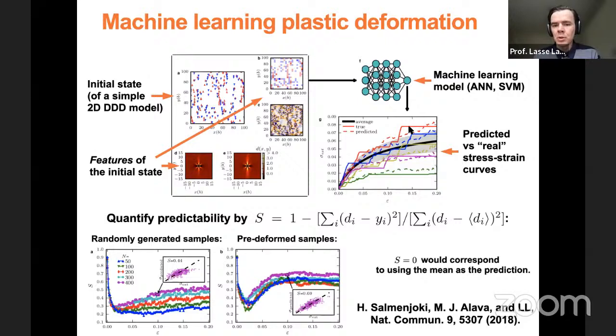And to make this statement more quantitative, what we look at is a quantity which here we call S. It's actually the coefficient of determination. You could also call it R squared, which is the squared error of the prediction in units of the sample variance with a minus sign, and then you add one. So the perfect prediction, where this prediction error is zero, would give you S equals one. S equals zero would mean that you just predict that all your samples behave like the mean sample. So that's a very, very crude prediction. We of course want to do better than that.